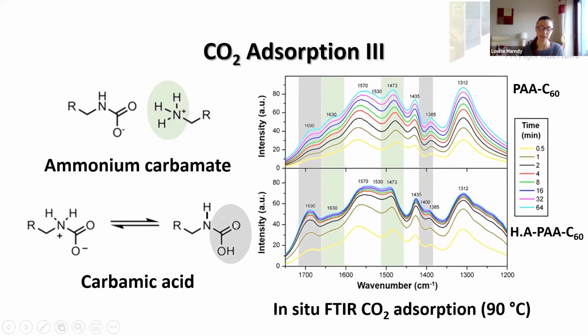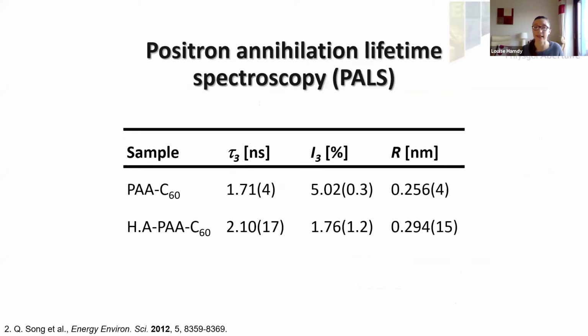So we have established that the hydrophobic additive improves adsorption at lower temperatures, but we want to quantitatively determine the origin of this enhanced uptake. So for this, we use positron annihilation lifetime spectroscopy. Now, this PALS spectroscopy measures the lifetime of the orthopositronium state to calculate the free volume of our material. And this is an ideal technique to measure the nano and mesoscale void volume. So the lifetime here is correlated with the size of the void volume. The longer the lifetime, the bigger the void.